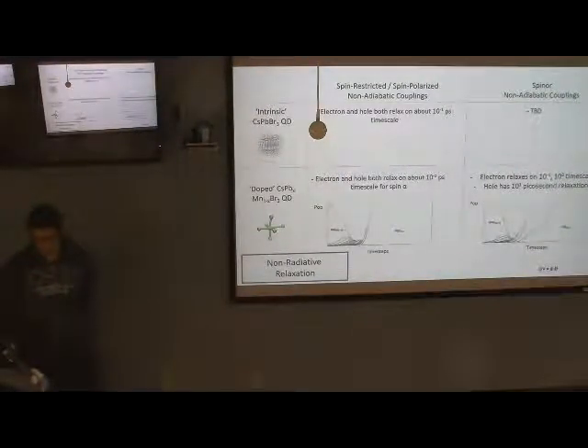I haven't fully completed these yet, because I'm working out some bugs with the code and the data. But we just start with our intrinsic dot, comparing spin-restricted and spin-polarized non-radiative relaxation. They both relax to the band edges of the quantum dot on about 10 to the 1 picosecond time scales. I'm not sure how that compares to the literature off the top of my head. I can't remember what the reported values are. Let's look at the spin-orbit couplings for the intrinsic dots. It's work in progress. So it's a sub-picosecond range, right? Yes. I think my initial data showed that they're about on the same time scale, but I don't fully trust it yet. And then with the doped dot, that's where the interesting non-radiative relaxation occurs.